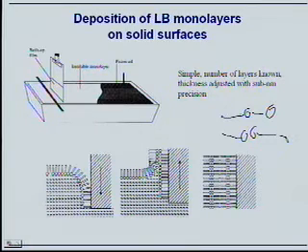So this is one of the most powerful ways of depositing thin molecular films on surfaces. And it works beautifully. You can deposit 50 layers if you like. Say these 50 layers are going to be 100 nanometers thick. So I'm going to deposit a 100 nanometer thick layer by dipping the plate 25 times into the surfactant layer. It's a very simple, very beautiful kind of experiment, directly relating to nanoscience. This is the way to deposit thin films. So, just a little bit about self-assembled monolayers by direct adsorption on surfaces.